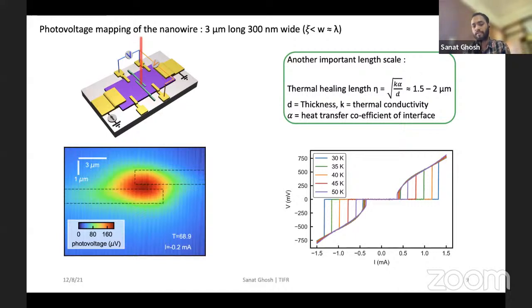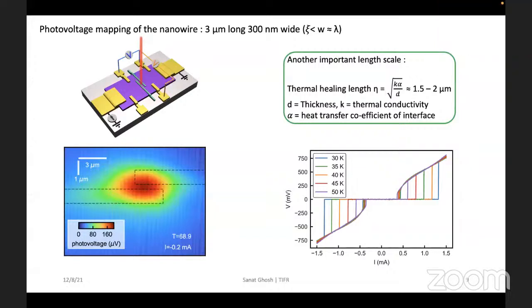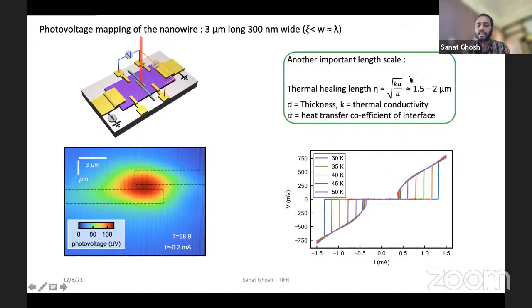But apart from the two length scales that I already mentioned, the coherence length and the magnetic penetration depth, there is another important length scale in this problem, which is the thermal healing length. Yeah, I'm about to finish. It is about 1.5 to 2 micrometers, and since the nanowire that I show here is of similar length, we don't see these multiple hotspots of the photovoltage.